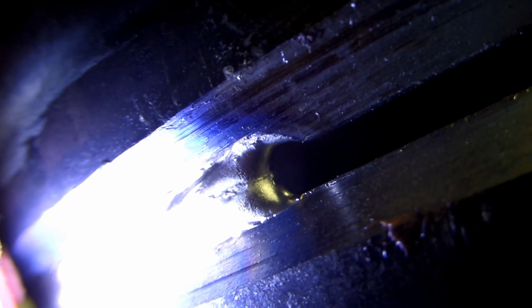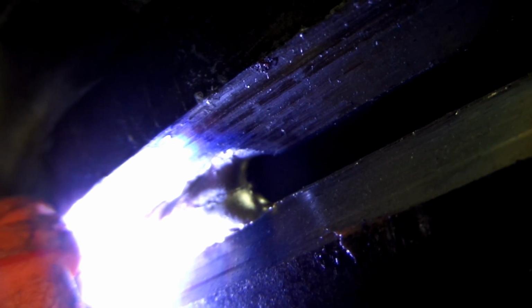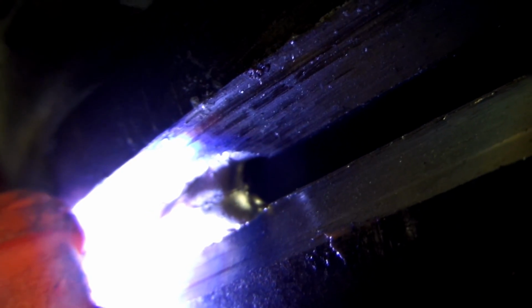I'm on the leading edge with the TIG torch, unlike stainless and carbon or chrome, where I'll be in the middle of the puddle. But I'm on the leading edge, I'll open a keyhole. I'll add the fill metal to the leading edge close to the base on the inside of the pipe. And then on the outside of the pipe will be my TIG torch.